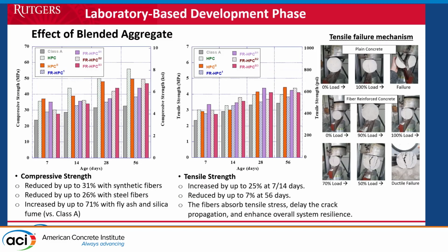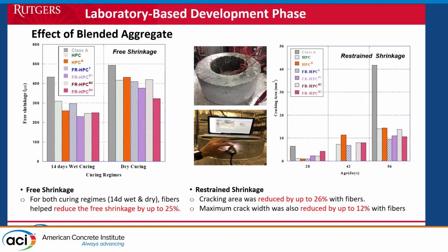With the blended aggregate, we got very good results, mainly in the compressive strength and the tensile strength. The difference with the fibers is that you had a lot of ductility post-cracking. Maybe this is not very evident for the concrete deck, but our hope was that the fibers will keep the crack width narrow. So the idea was to put concrete decks made out of HPC, and at the same location put concrete decks made out of fiber reinforced HPC, and do a one-to-one comparison, because they're under the same loading conditions and same environmental conditions.